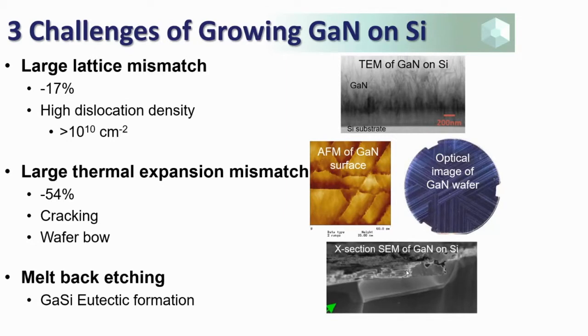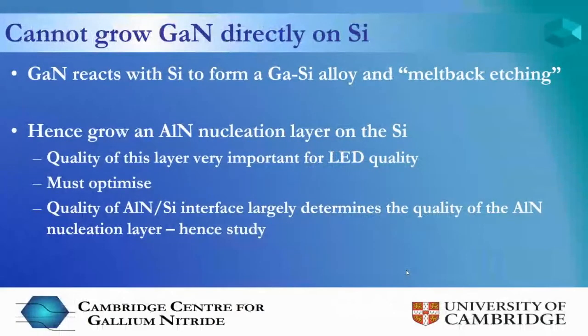And then the third problem to solve is, when you put gallium nitride on silicon, you actually get a reaction, a chemical reaction between the two. You get a gallium silicon eutectic formed, that gallium silicon compound formed, and you don't want that as well. So these are 3 major problems. And when I propose this to the research student, I say it's a big challenge. And people would say to me, "You're crazy, Colin, you're crazy to try this, because these problems, you'll never succeed." And this very good research student actually did succeed.